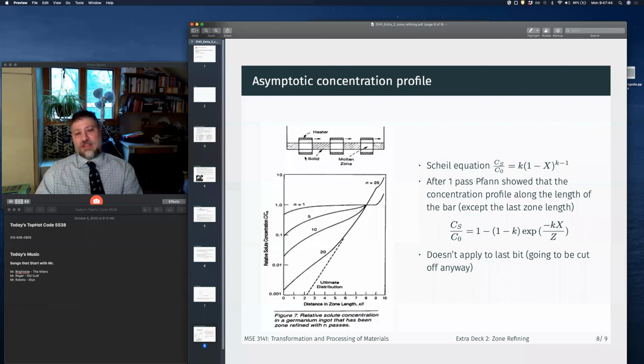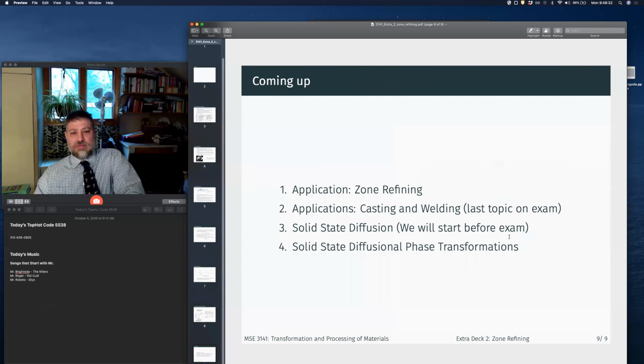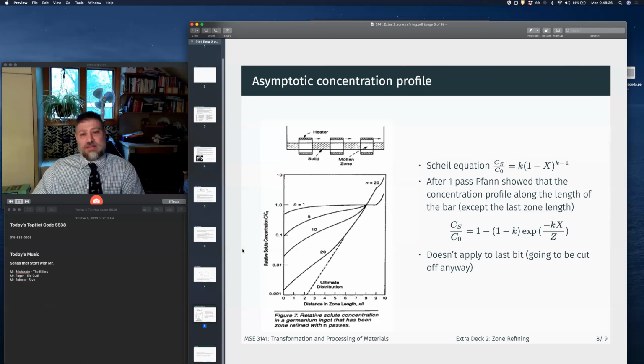But the cool thing here is, because this composition zone is so small, and this melted liquid is so small, and because it's moving, we get really good convection currents. So perfect mixing is a really good approximation. So we could just use the Scheil equation to predict the composition. And if you just keep running a Scheil analysis over each one, we hit this steady state that's going to depend on a couple things here, where Z is the width of the melt region. That's zone refining in a nutshell.